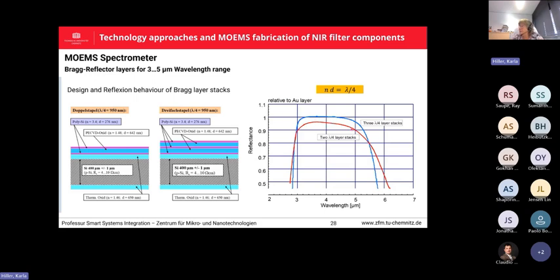And we see even for the 2-layer stack, we have about 95% reflection, which is enough for our filter application. 100% would not be so good because then no light can transmit through the filter at all. And if the reflection is too low, then the transmitting wavelength is low, and also the bandwidth of the filter is much wider. The resolution is not so good. So that's why a range between 80 and 95% would be ideal.